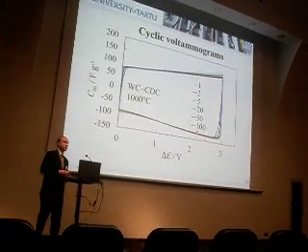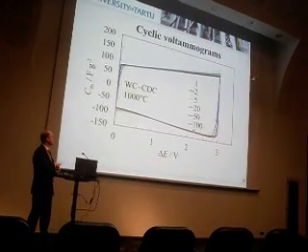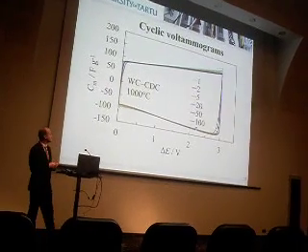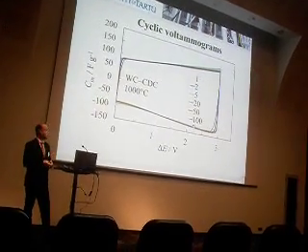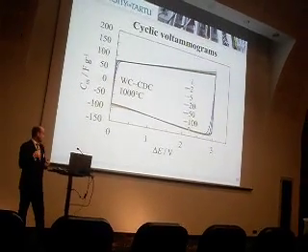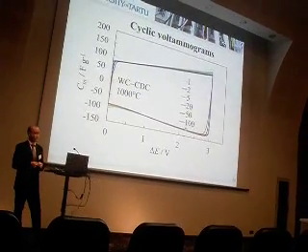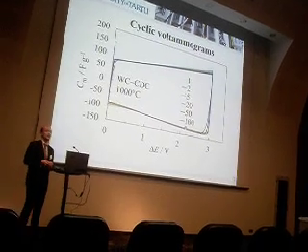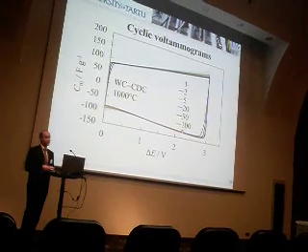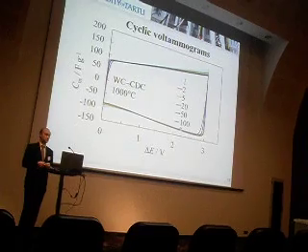And what was also very good with this material is that there were no deviations in these voltammograms, even with a scan rate of up to 100 millivolts per second, which indicates that the ions in the electrolyte can move freely in the mesopores, and there was no starvation in the electrolyte.